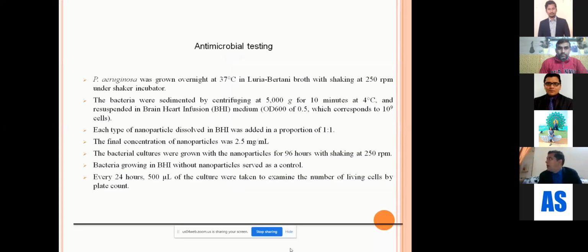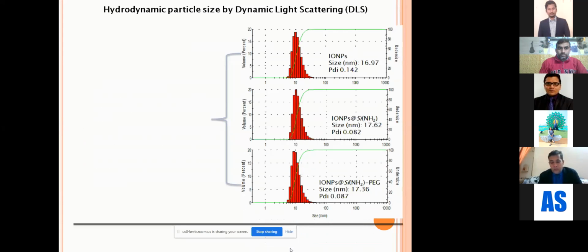But before going into the controlling of the Pseudomonas aeruginosa using these superparamagnetic iron oxide nanoparticles functionalized with silane with carboxylic group, or silane with the amine group, that is quaternary ammonium compounds, we actually tried characterizing the size of the nanomaterials we developed, and we could see that the magnetite nanoparticle size range was around 16 nanometers.